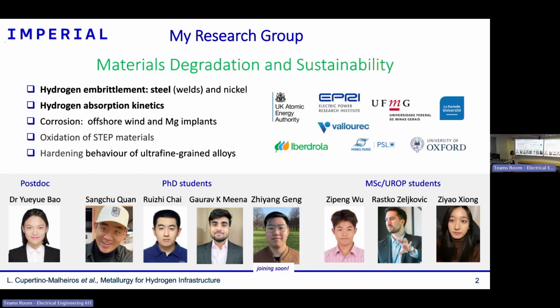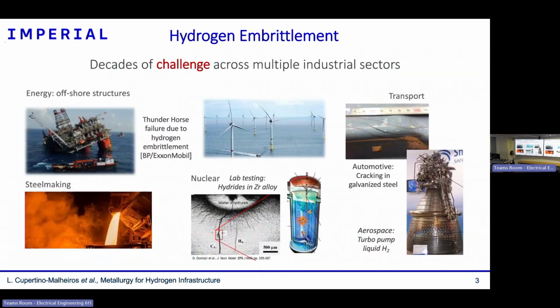And before I move to the actual research, I would like to explain to you why hydrogen embrittlement is a big problem. So hydrogen embrittlement is not a new problem, it's quite an old problem and has been a challenge along many decades across multiple industrial sectors. And here I'm showing some examples with those images on the early days of steel making, when they couldn't remove that much hydrogen inside the liquid steel, and when it was cast, hydrogen gas was inside, causing cracking.